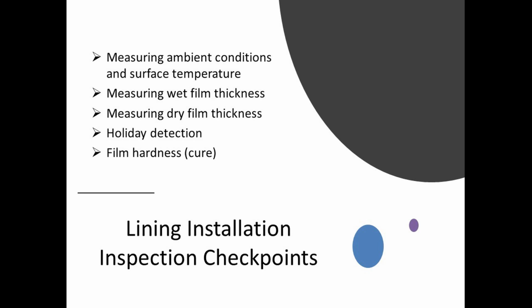Now we're going to move over to some things to look at as far as lining application or coating application is concerned. First one is measuring the prevailing conditions of temperature and humidity and so forth. This is very important because we have to be able to comply with the coating manufacturer's minimum and maximum temperatures and relative humidities. And we also have to make sure that we don't have a dew point surface temperature problem as well. So these conditions should be measured ideally before we start mixing the coating or lining material, if it's a multi-component material, and then throughout the process as well.